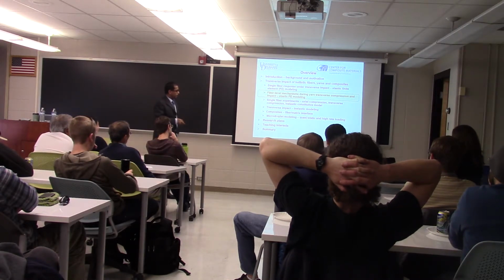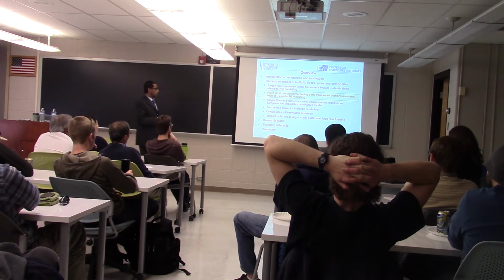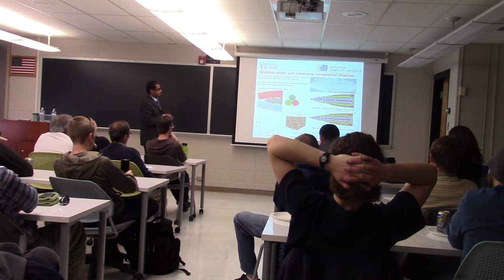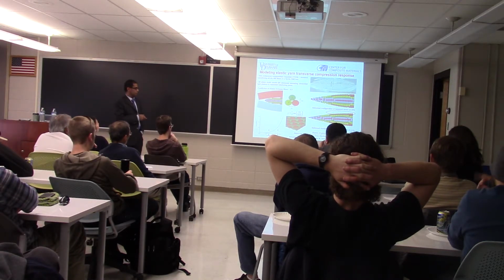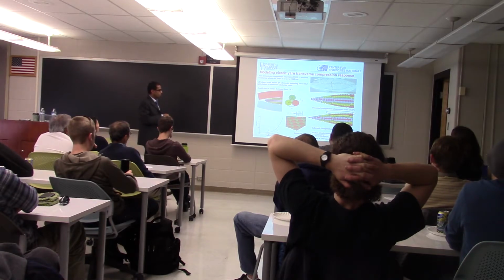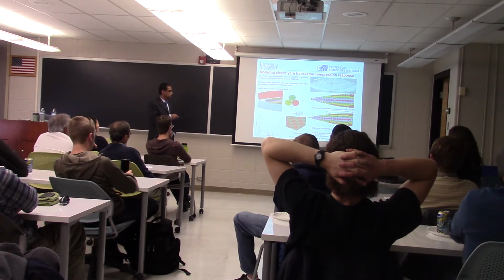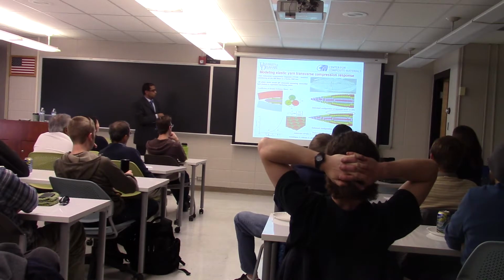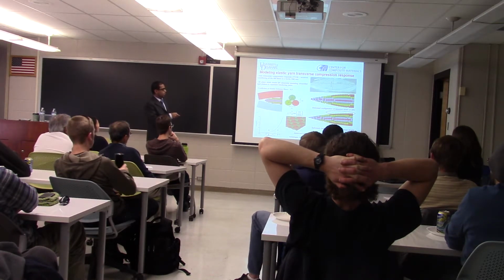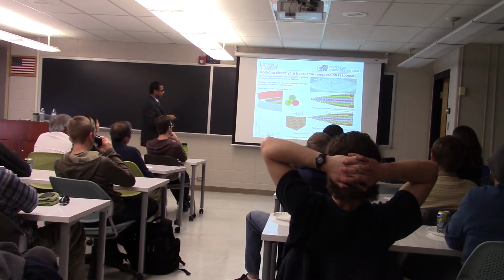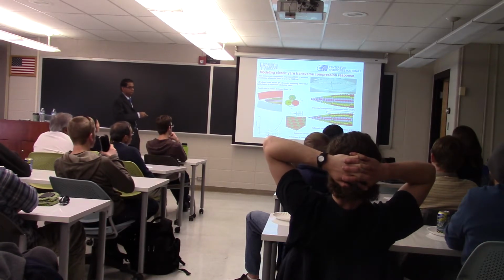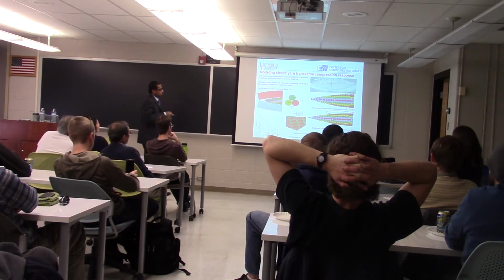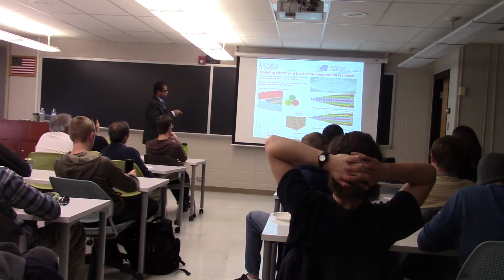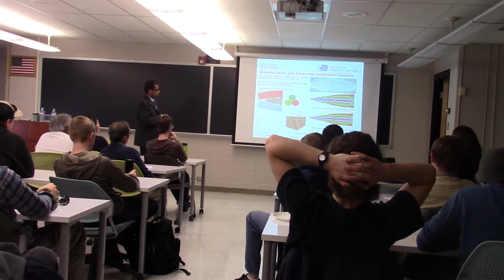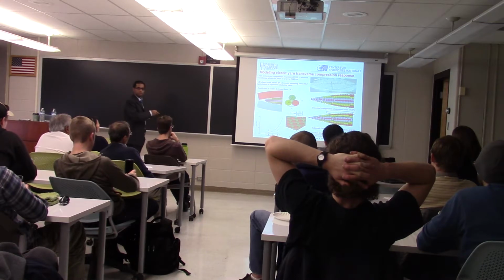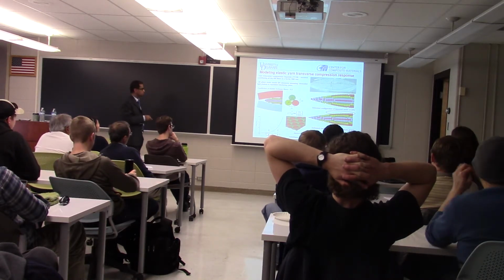Now, to understand the fiber level mechanisms, we model this yarn transverse compression at the fiber length scale by explicitly modeling all the individual fibers in a yarn. This is a 2D plane strain model. Here we approximate the cross section of the yarn as an ellipse, and the fibers are arranged in a hexagonally close packing. To provide the constraints provided by the adjacent orthogonal yarns, we model the platens in a sinusoidal shape based on the fabric architecture.